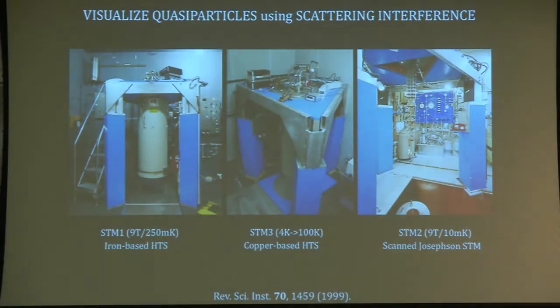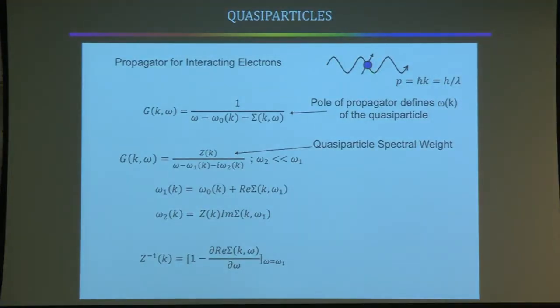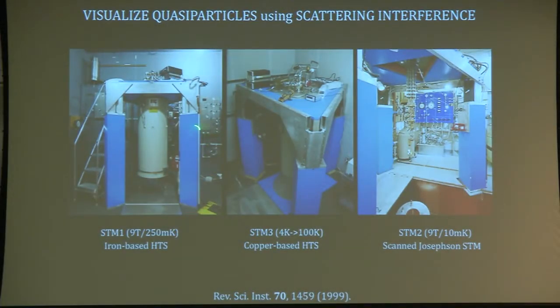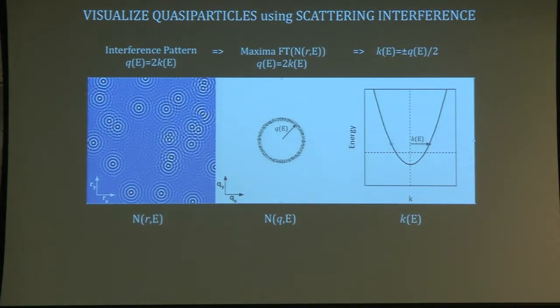Okay. So we have machines that can visualize quasi-particles. That's why I'm here. They're spectroscopic imaging STMs. We've been using this one for what I want to tell you about. And here's what we can do. Look in real space. There are impurities. If there are coherent quasiparticles at every impurity, they're scattering interference. An incoming quasiparticle scatters from the impurity, reverses momentum, and then interferes. The incoming and outgoing quasiparticle interfere. The interference pattern at each impurity has a q vector, that's 2 pi over its wavelength in real space, which is related to twice the k vector of the eigenstates, because you had to go from k to minus k to produce the interference pattern.